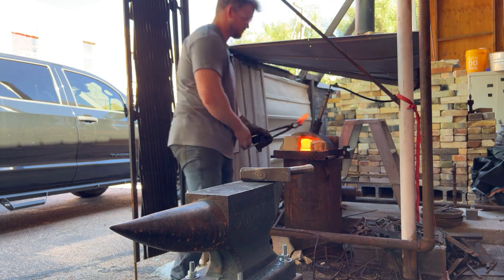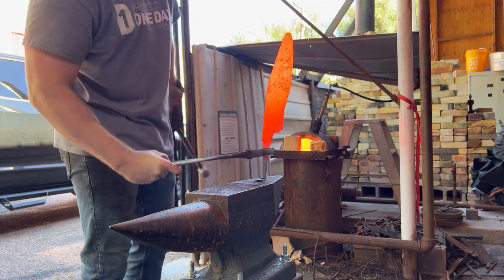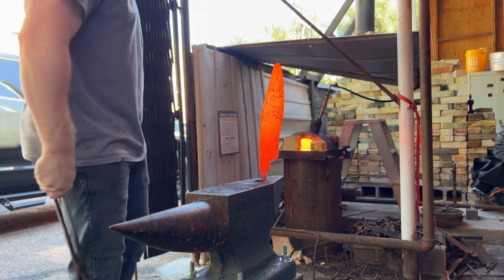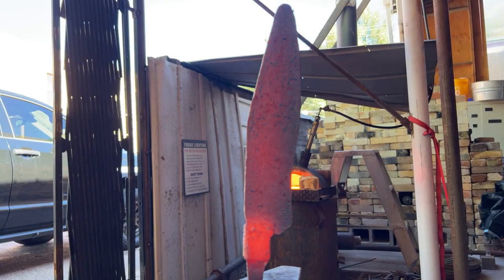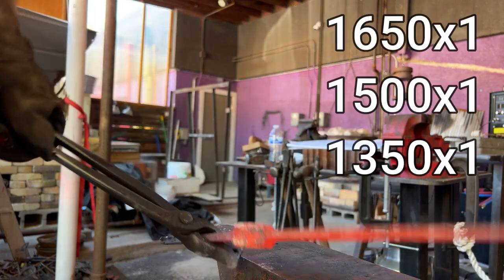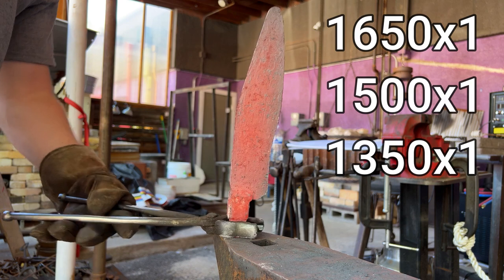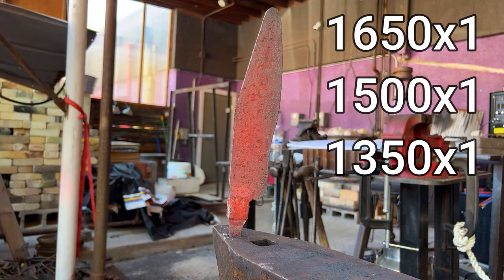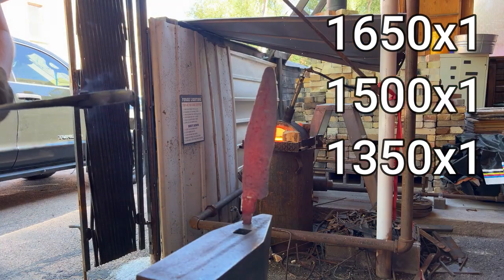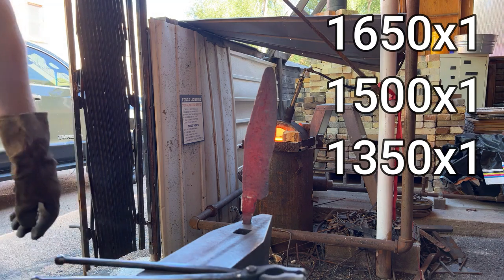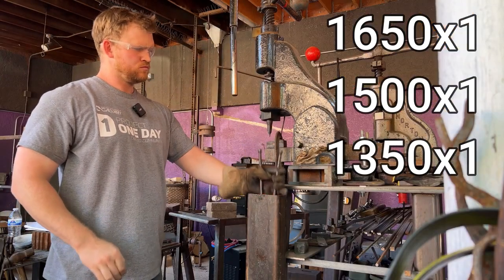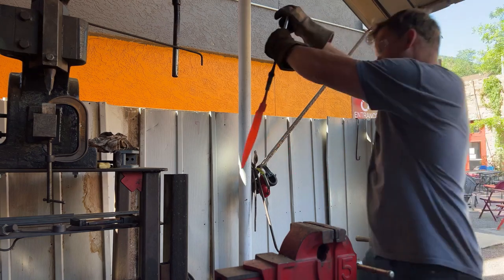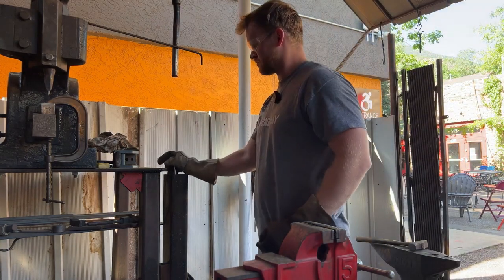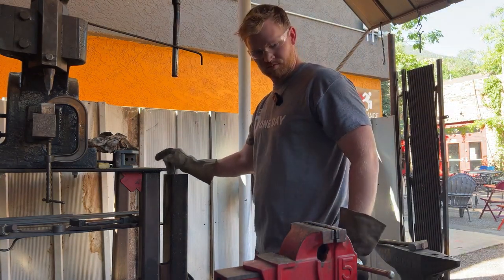Heading into the heat treat, and the heat treat consists of normalizing, quenching, and tempering. What I'm doing right now is called the normalizing or thermal cycling. That first heat was at or around 1650 Fahrenheit, and I cool it in still air to black. Then 1500 and 1350, again, cooling it in the still air to black. I heat the oil up with a piece of scrap, and I quench at 1500 degrees.